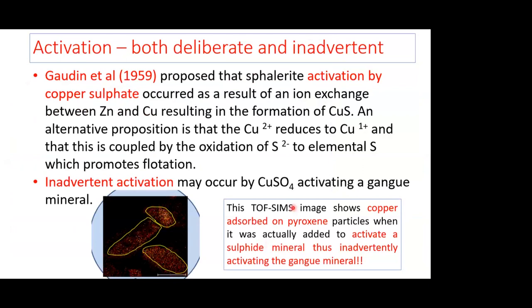Activation, there's a huge amount of literature on activation. Gaudin proposed that sphalerite activation by copper sulfate occurred as a result of ion exchange between zinc and copper. There are other views that this really is a story of the reduction of copper 2 to copper 1 accompanied by the oxidation of sulfide to elemental sulfur. So there's a lot of literature, some of it confusing, on the relative roles of copper sulfate as an activator, as an example of an activator.